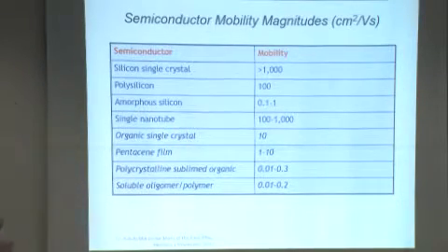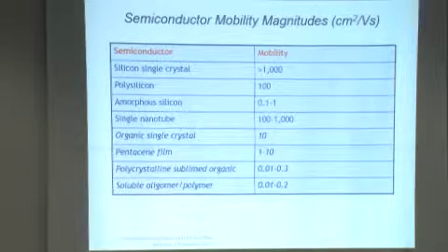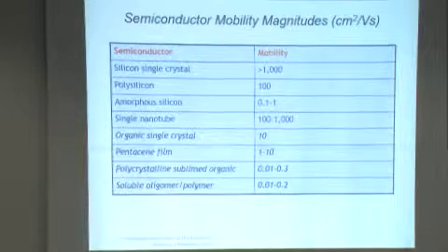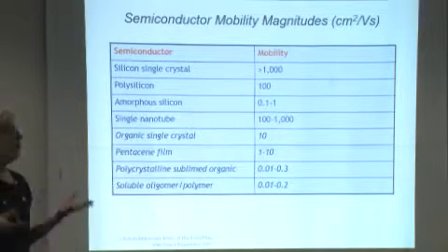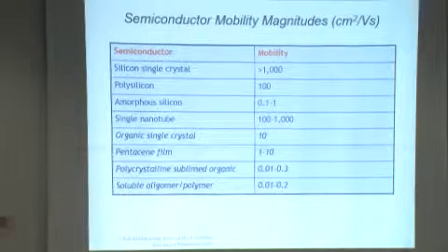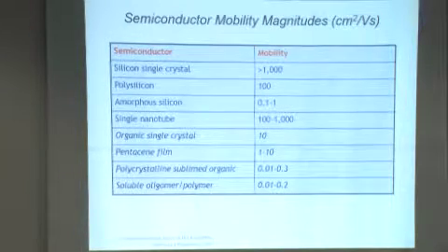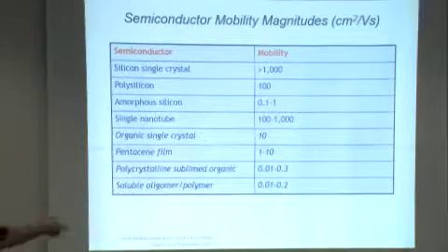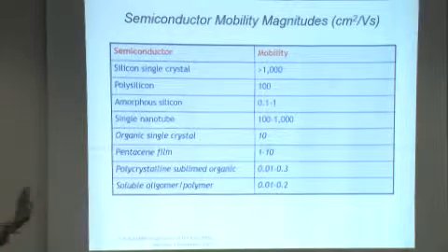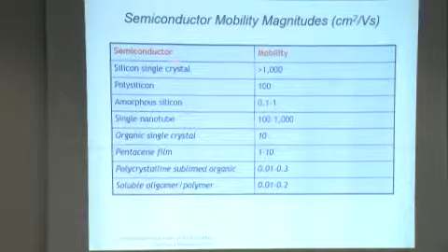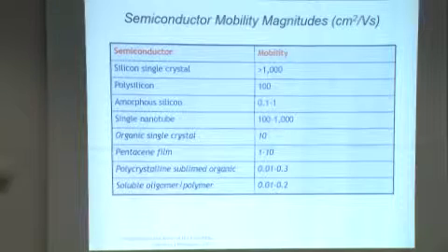All right, so what's the determining factor, the figure of merit, for semiconductor technologies? The particular parameter that is being looked at is the mobility, measured in centimeters squared per volt second: how quickly does an electron or a hole, a charge, travel through a particular film when you apply an appropriate voltage. Single crystal silicon, which is used for IC devices that are ubiquitous, has a mobility well over 1,000. So in terms of polymer technology, replacing single crystal silicon, forget it. That's not going to happen.